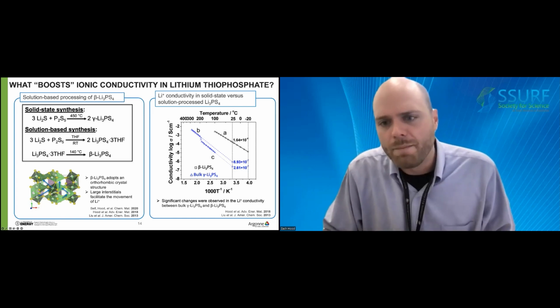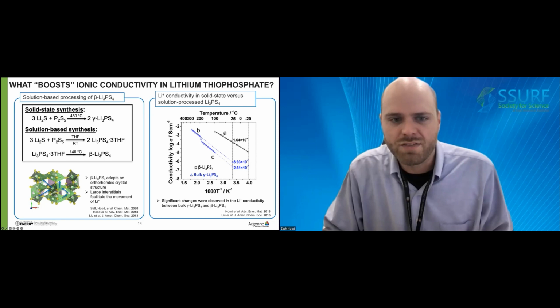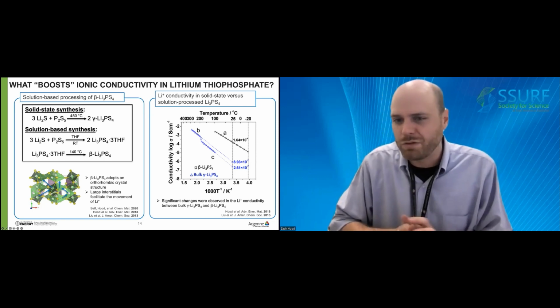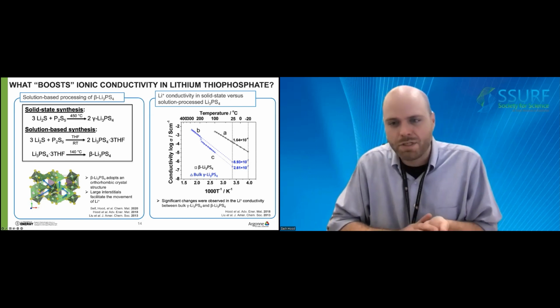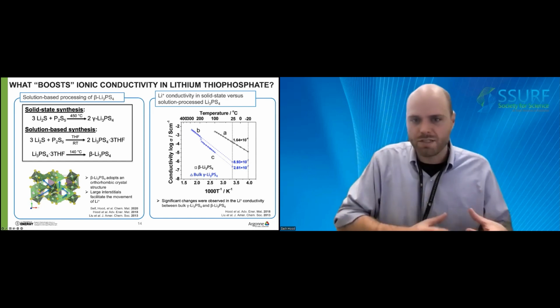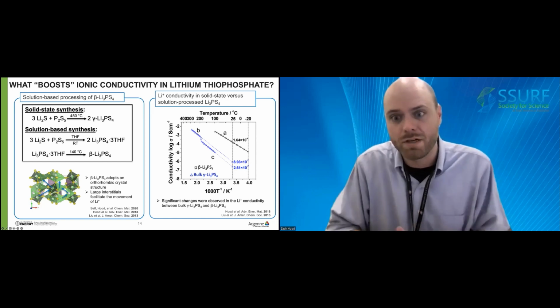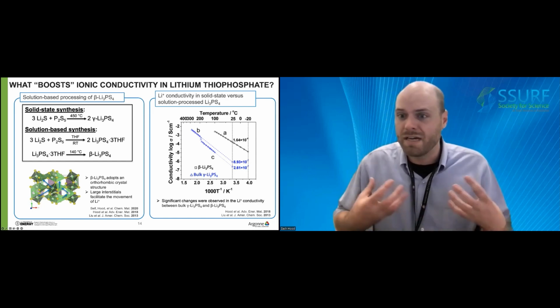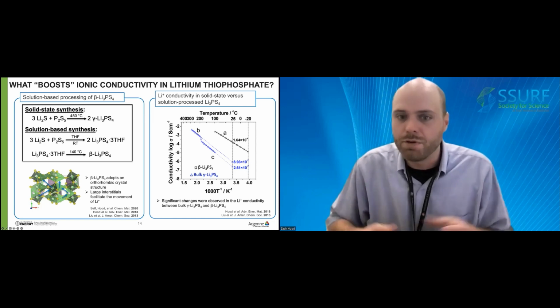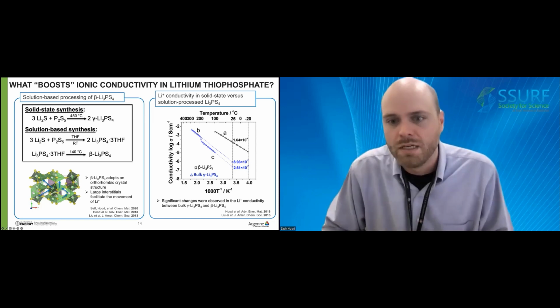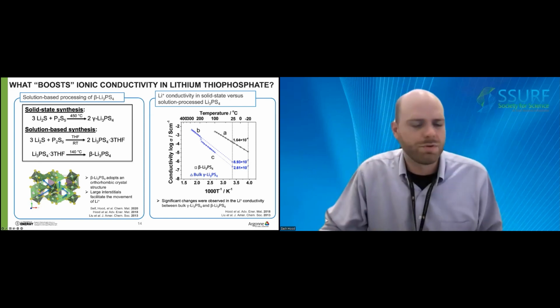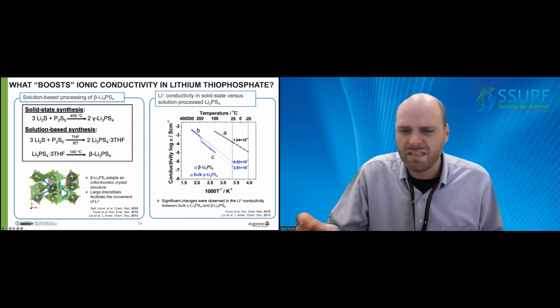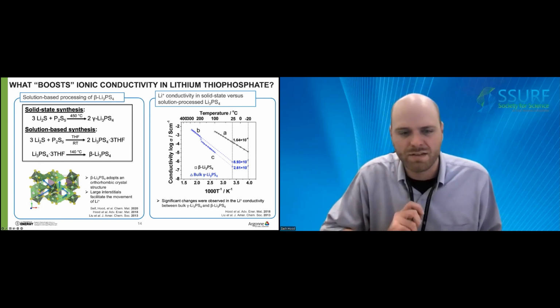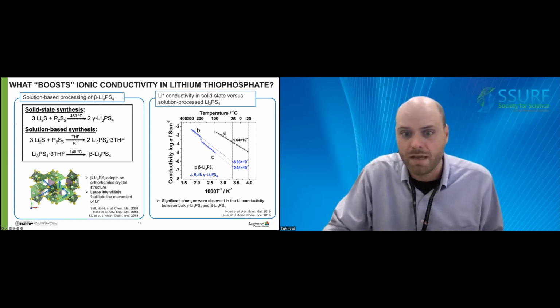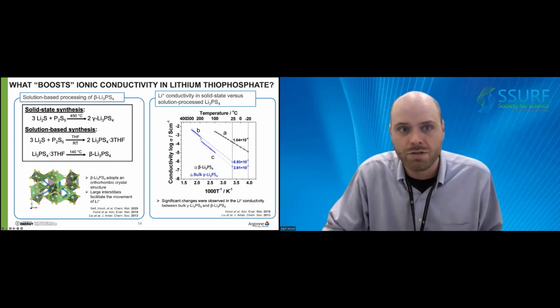conductivity. The bulk gamma phase of lithium thiophosphate has a room temperature ionic conductivity on the order of 10 to the minus 7 Siemens per centimeter, whereas solution processed lithium thiophosphates have room temperature ionic conductivities on the order of 10 to the minus 4 Siemens per centimeter, an improvement of about 3 orders of magnitude. But what is the root cause of this improved lithium ion conductivity? Or more clearly, can we interrogate these materials at the nanoscale to better understand their structure property relationships?